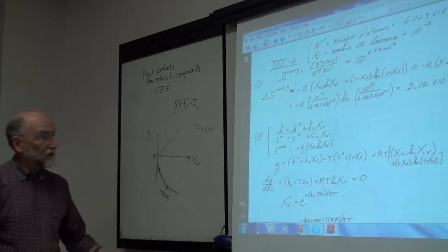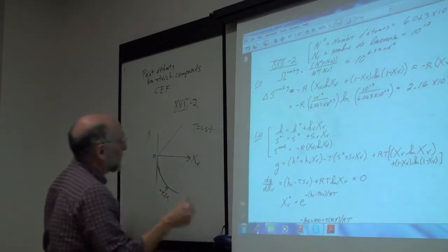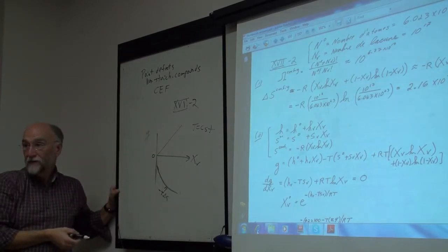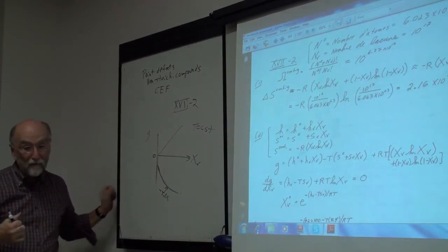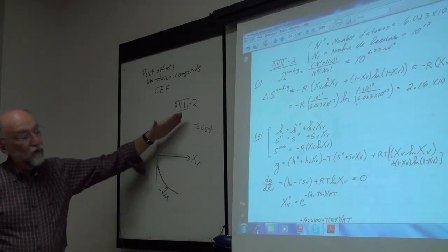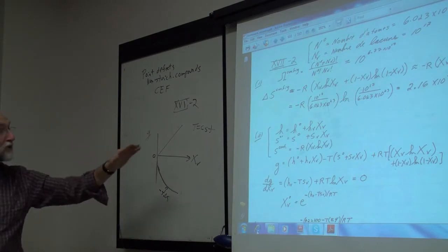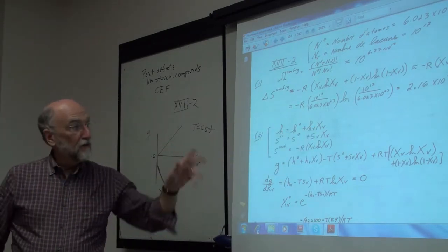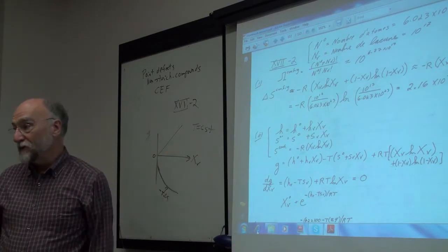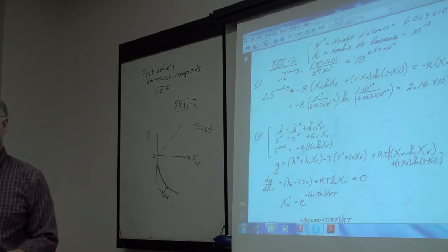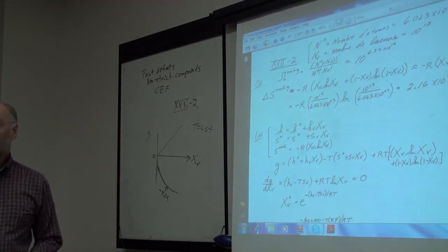At any given temperature, the first term here will have a positive slope because forming a vacancy is a positive thing. You remove an atom, it takes a positive energy. So every time you form a vacancy, you're forming a positive energy, and at least in a dilute solution it is basically linear, because the vacancies don't see each other, so every vacancy you add gives you exactly the same contribution as the previous. Henry's law certainly applies at 1 part per million.